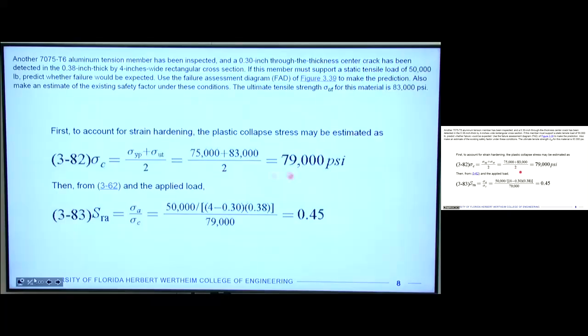So first let's calculate the plastic collapse stress, sigma C, which is the average of the yield point and the ultimate strength. This is the same material that we had in the example problems from the prior lecture. It has a yield strength of 75 kpsi, and we'll average that with 83, the ultimate strength, so we get 79,000 psi.